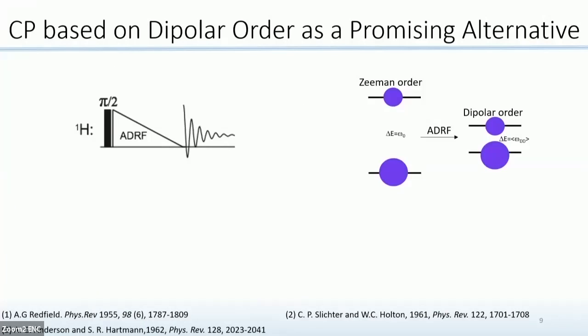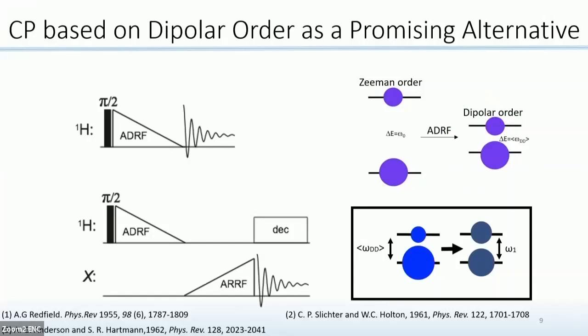So we were looking for an alternative. And then we came by a pretty old idea of adiabatic demagnetization in the rotating frame, or ADRF, which is used to generate dipolar order. Essentially, in the sequence, we convert Zeeman order adiabatically to dipolar order. In Zeeman order, the order of the spins is determined by the external magnetic field, whereas in dipolar order, the ordering of the spins is determined by the local dipolar fields of the protons. And the nice thing for us about dipolar order is that once you generate it, it lives for a time scale of T1D. And the upper limit for T1D is the proton T1. But then once you generate it, you can also use it for ADRF CP.